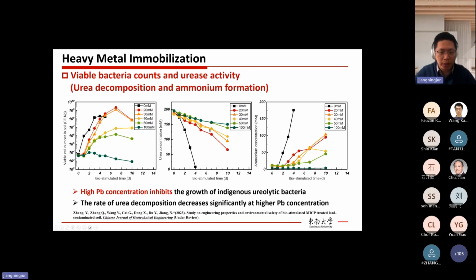Then with the increase in the contaminant concentration, the decomposition rate becomes smaller and smaller. But interestingly, even in the 100 millimole case, the most severe case, the urea could still decompose, although very slowly, but it keeps going. It means that if we leave it for a sufficiently long time, the ureolytic reaction could still happen, although at a slow rate. Therefore, ammonia concentration is similar to urea for the no contaminant case. So we see a lot of ammonium. Then with the increase in contaminant concentration, the ammonia concentration becomes smaller.